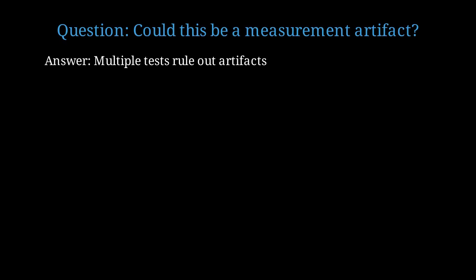Now you might ask, could this be a measurement artifact? Could there be something wrong with our experimental setup that makes it look like the resistance is zero when it's really not? Excellent question. This is exactly what good experimentalists must consider. Onnes performed multiple tests to rule out artifacts. He verified that changing the current didn't affect the result. He checked the voltage measurement system. He tried different samples. The zero resistance was real.